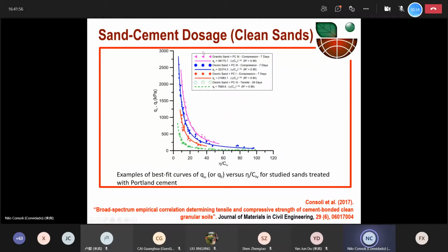We can see that in each case, for example, this granitic sand from Portugal, where we tested unconfined compressive strength at 7 days using early strength cement, we can get a unique curve for different dry unit weights and different amounts of cement. The curve is the same. And we tested the Osório sand from Brazil with different cements under compression and also under tension, and with different curing times. Each one has its own curve, but in this case we can check that the power at the top here is almost the same.